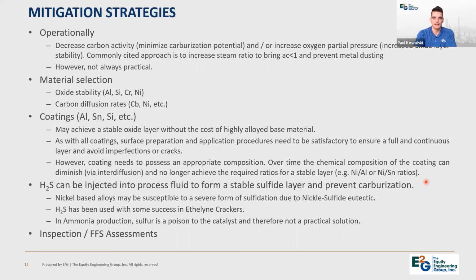However, based on the environment and the chemical composition of the base metal, at least one thing that needs to be considered is nickel-based alloys in high temperature sulfur environments may be susceptible to a severe form of sulfidation. And really, this is due to the formation of a low temperature nickel sulfide eutectic. So basically this phase is molten at these operating temperatures, and then the material itself is exposed, and there's no further protection from the sulfide layers. So if you're going to consider H2S injection into a process stream where you have nickel-based alloys, this certainly needs to be considered, and make sure that this form of sulfidation won't occur.